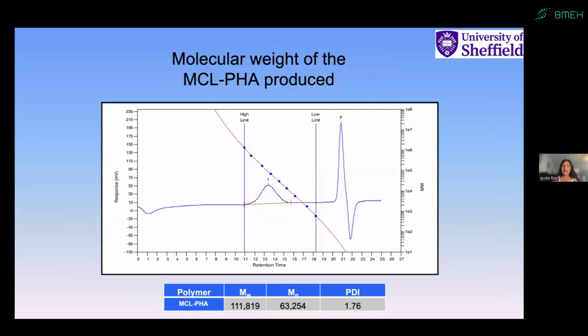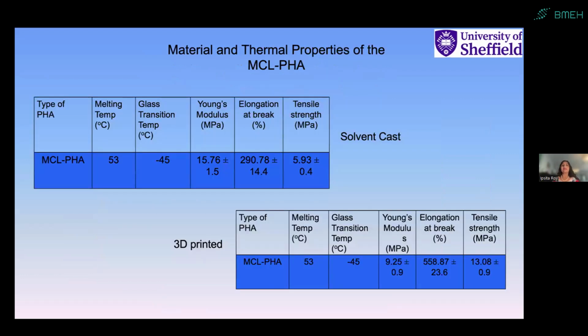Here is a GPC, and you can see that the molecular weight is also measured every time we produce the polymer. This is a typical medium chain length PHA, and here you can see it is much lower in melting point, only about 53, and the Young's modulus is only about 15 megapascal, which is again much lower than P3HB. So although both of these polymers are polyhydroxyalkanoates, you can see how different they are as far as the polymer is concerned.